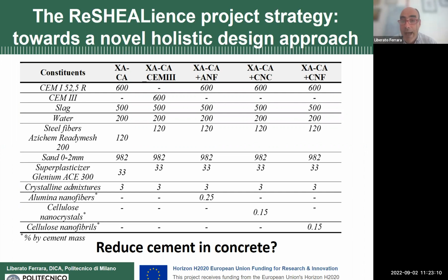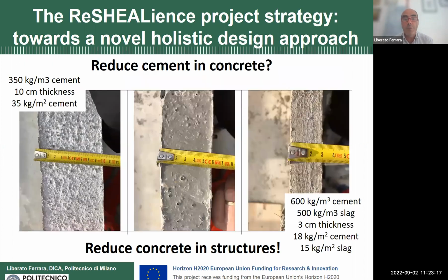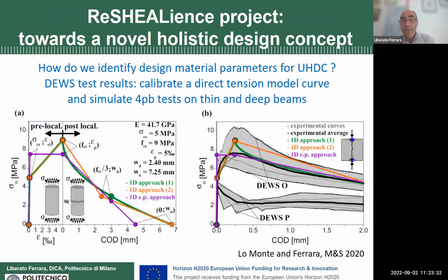So I halved the use of cement in my structure, going from ordinary reinforced concrete to UHPC material. And these are the details of the calculations, focused on each of the applications that we had in mind. You can see the measured dimensions of our structural elements. Why was this possible? Well, this was possible because our UHPC material, our UHDC material, they feature a one-of-a-kind strain hardening behavior.